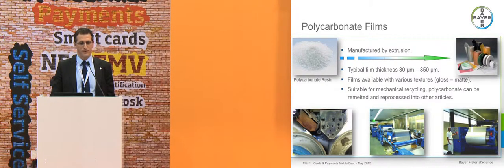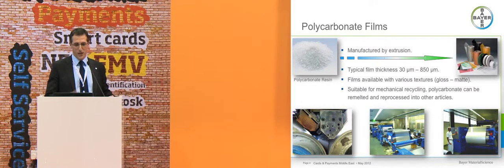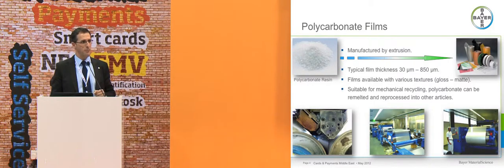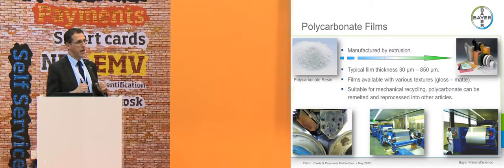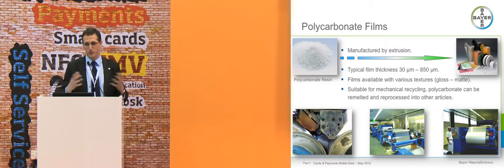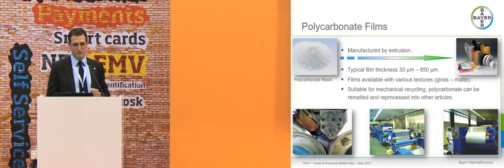So polycarbonate films, how are these made? We make the polycarbonate films by a process called extrusion. We melt the polycarbonate granules, and by pressing them through a die, you can see the pictures down there, the film gets its shape. By embossing it with rollers, we can create various surface qualities onto the polycarbonate film, from gloss surfaces up to matte, or a combination of gloss, matte, and so on.